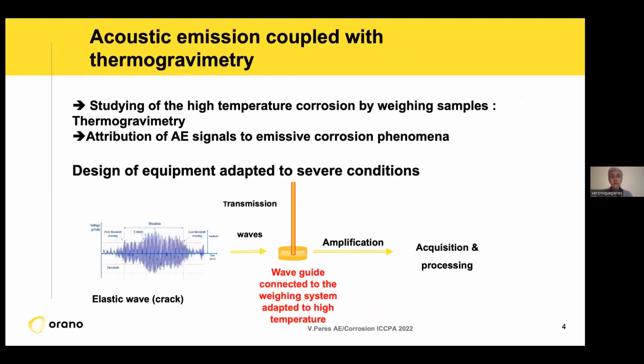So we decided to make a specific tool and to make the association of acoustic emission with thermogravimetry. We normally study high temperature corrosion with thermogravimetry by weighing samples, and at the same time we want to attribute events to corrosion phenomena. So we designed special equipment adapted to severe conditions. If you look at these graphs, you can see some bursts coming from the samples, and these waves are transferred to a waveguide connected to the weighing system. We amplify the noise from the sample, and we can acquire and process the data to get the information.